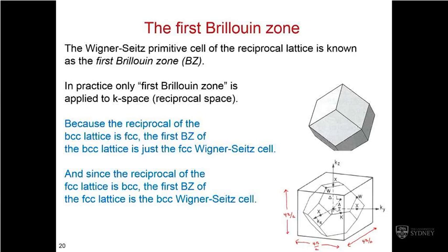This is the Brillouin zone of the BCC, okay? And within this shape, we defined some high symmetry lines and high symmetry points. They are, by convention, given names like the X point. There's another X point because it's the same. And you have the K point here, which is on the side of this sort of hexagon. L point is in the center face of this hexagon.